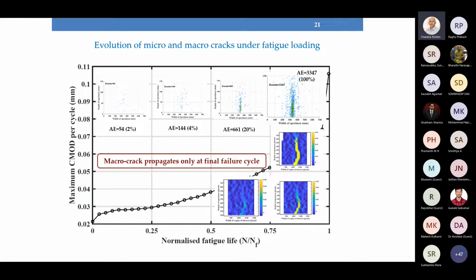Okay, and this image showing the crack profile on the surface, we see there's hardly any crack propagation. This is taken one cycle prior to failure, and this is at failure. So what we see here is just before failure, all these micro cracks coalesce and form a major crack, which is shown by these yellow dots here. Okay, the higher energy events.